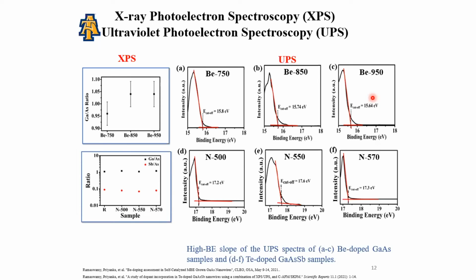The lowering of the work function, manifested by a positive shift in the binding energy of the UPS spectra of tellurium-doped gallium arsenide antimonide nanowires grown at the gallium telluride cell temperature of 550 degrees Celsius, revealed the sample to be a heavily N-doped sample with a carrier concentration of 2.8 × 10^19 per cm³.